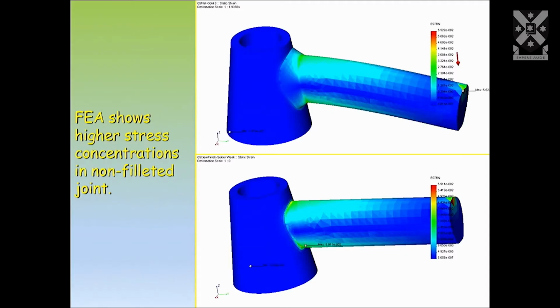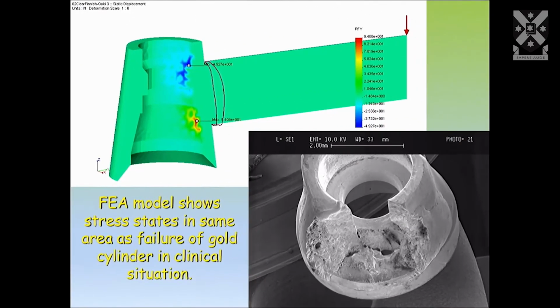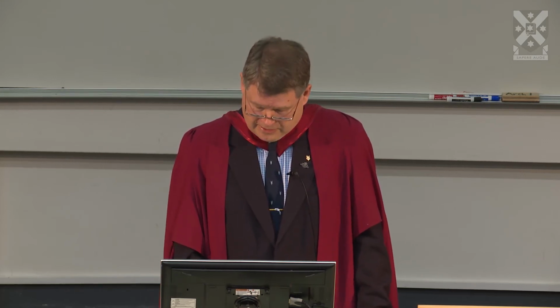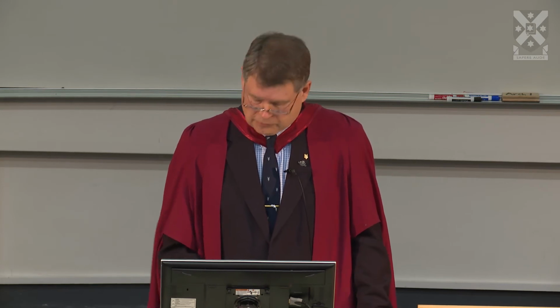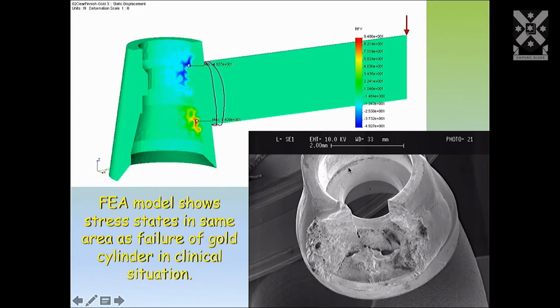So we modeled that using a mathematical model to look at the different designs in terms of a rounded sort of connection or a straight connection, as well as looking at the internal types of stresses. This helped us focus or imagine where these stresses would be focused. Was it to do with design or materials? It helps us to start to understand on a bigger picture where the stresses are focused and where the potential causes could be. What was also interesting, we found inside these failed cylinders, corrosion caused by crevice corrosion. So some of these stresses you see here, in actual fact, the failure had been initiated inside the implant from corrosion as well as on the outside.